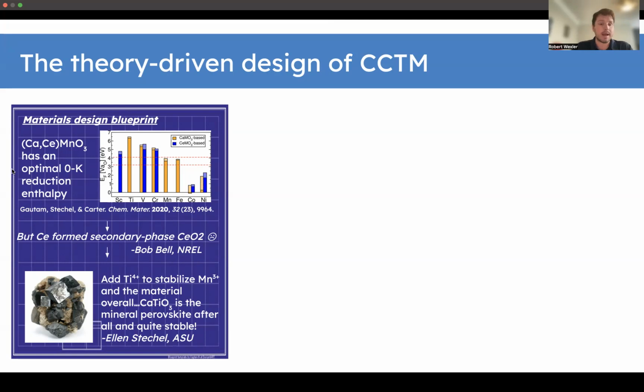manganese oxide has an optimal 0 K reduction enthalpy for two-step STCH. So that optimal reduction enthalpy, shown here on the y-axis, for different cations that could dope at the metal site, we focused on manganese, and these two red lines highlight a region of optimal efficiency for STCH. So you can see that there are only a few that actually fall in this window, but the one we were most excited about was this calcium, cerium, manganese oxide, because it actually fell on the 0 Kelvin convex hull.